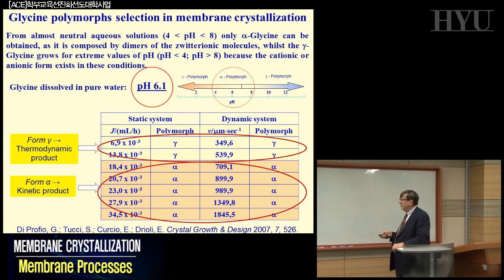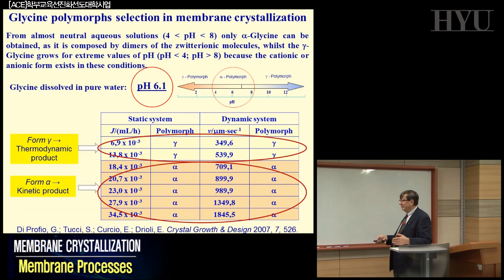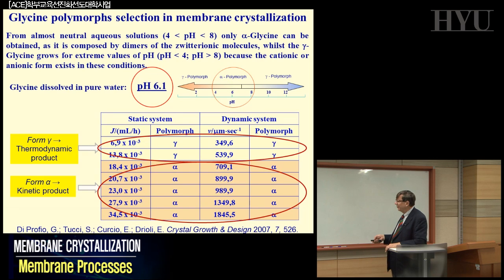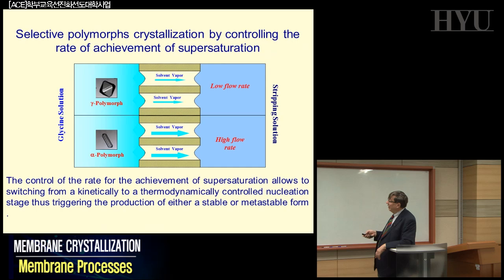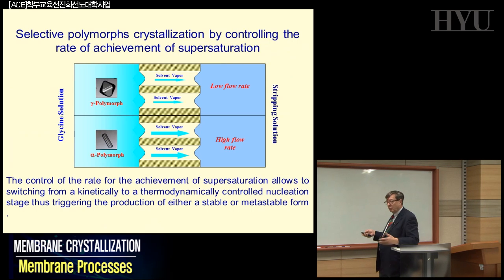It came out that in our study, we were able to separate alpha from gamma just by changing the transmembrane flux across the membranes. We learned that the form gamma was at low transmembrane flux, the alpha, if I remember, was at high transmembrane flux. If the flux was 7 or 13, or if the flux was 34, you have different results for gamma or alpha. And so that was one of the quite interesting examples of the result. And physically, that can be just a big difference, you see. That is the gamma, and that's the alpha.